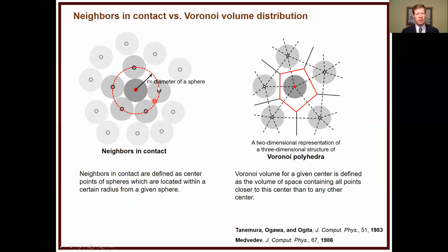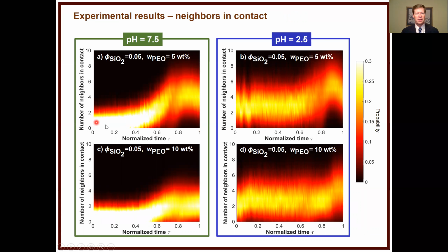So we can look at the number of neighbors in contact. We can look at 2R, or roughly 2R with a little bit of tolerance, and find how many particles are essentially touching this particle. And then we'll talk a little bit about Voronoi polyhedra, but it's essentially a similar analysis of figuring out the number of nearest neighbors, but non-touching. For the number of neighbors in contact, we've done this kind of spread plot where initially the average is between 0 and 1, and you can see very few particles have 2 neighbors initially. And then as it gets very dense, they're compacted close to each other, and then you get a very large broadening of this as things dry.